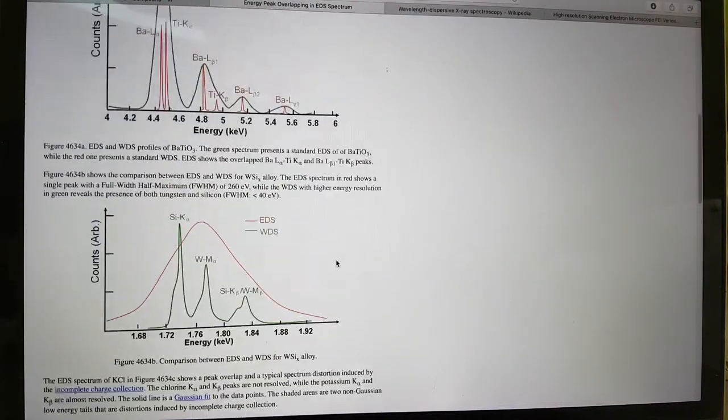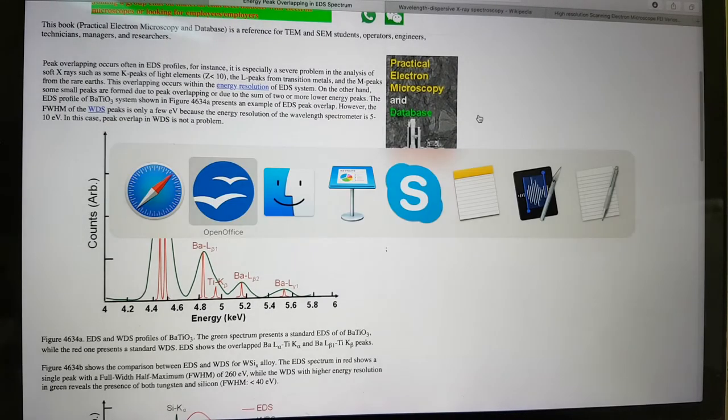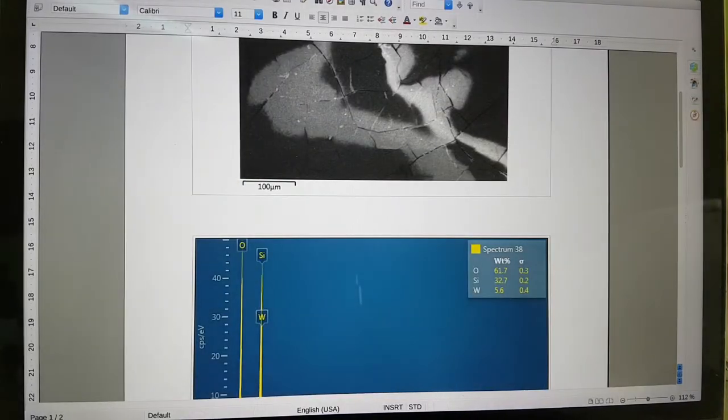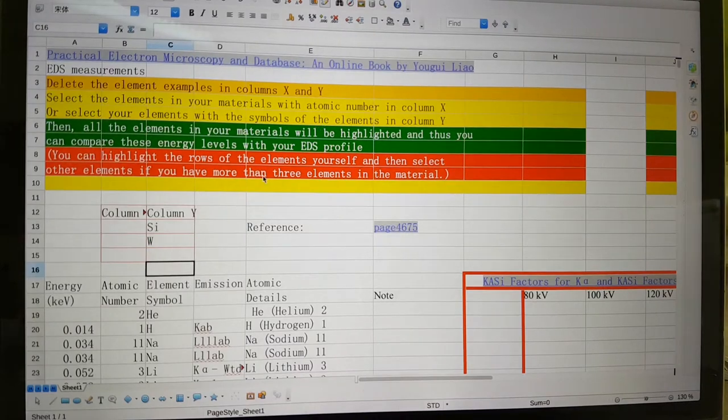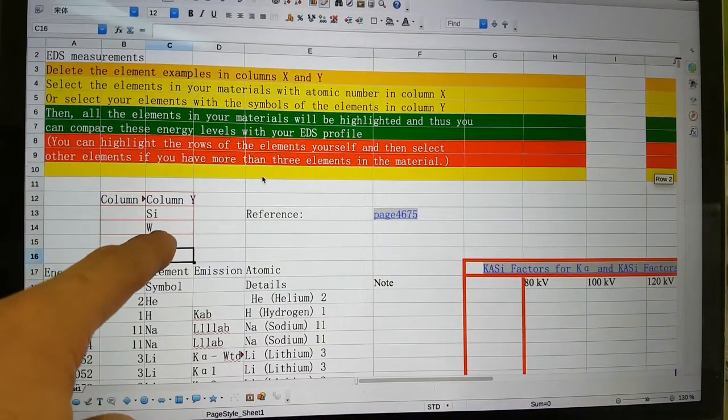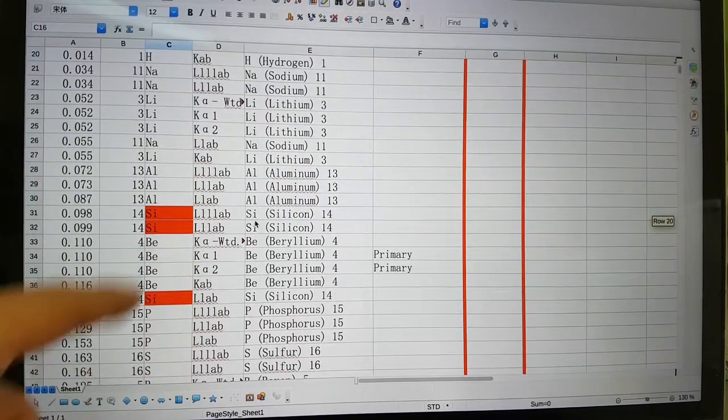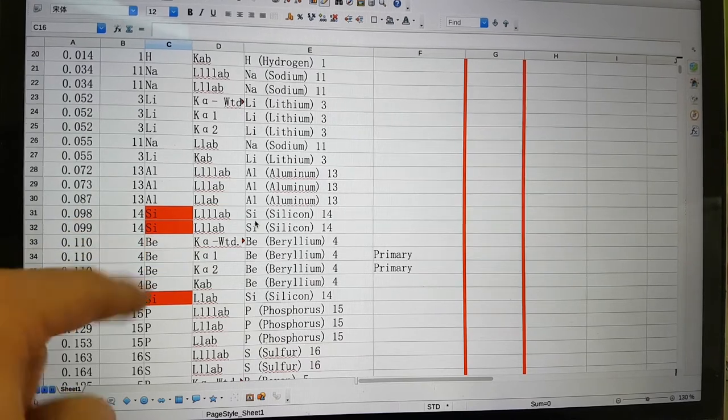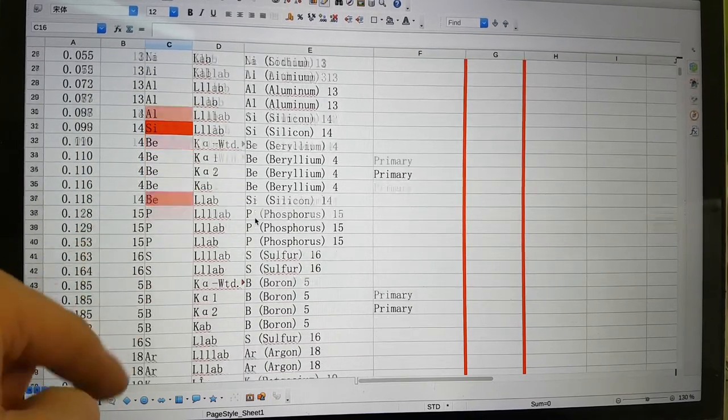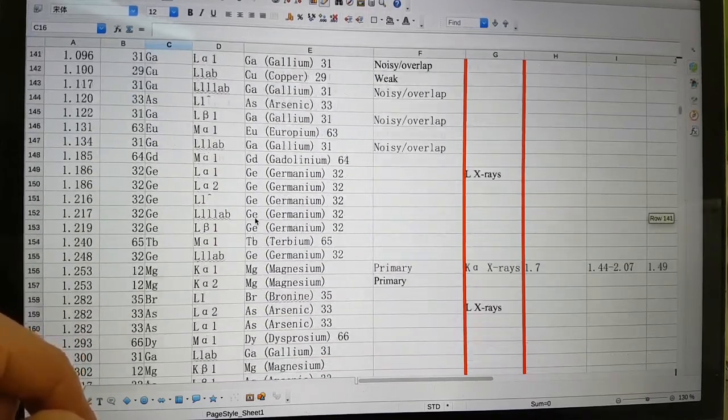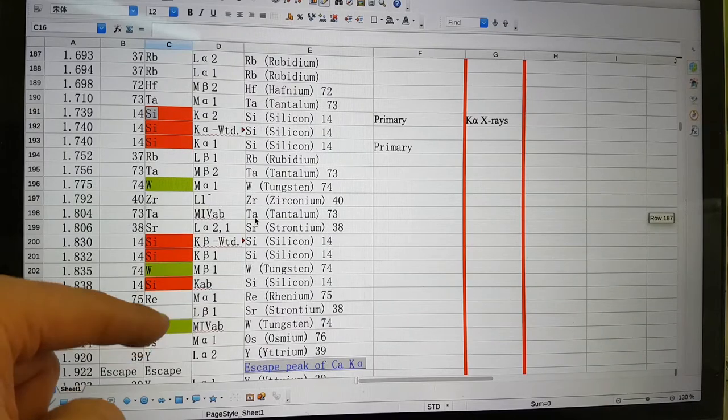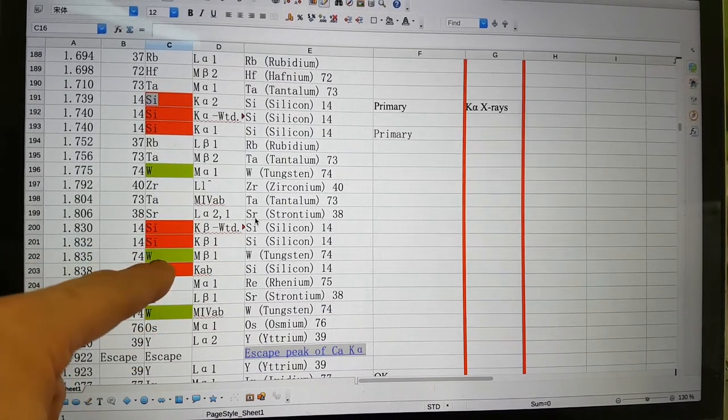Now, in this particular page, they have a link to a spreadsheet, which I will give a link to in the description of this video. And that spreadsheet is really rather cool because what it does allows you to insert into these two columns here, say silicon and tungsten. And it will then highlight in the list the x-rays that come back from the various things. So you can see there's no conflict here. The silicon's on its own. But the silicon and tungsten, if you go down to here, you can see here 1.83, 1.832. These are all very close.